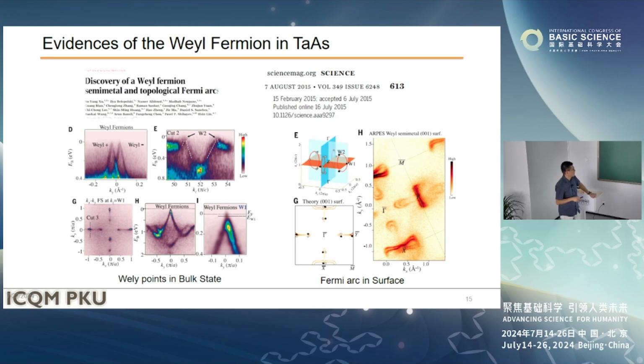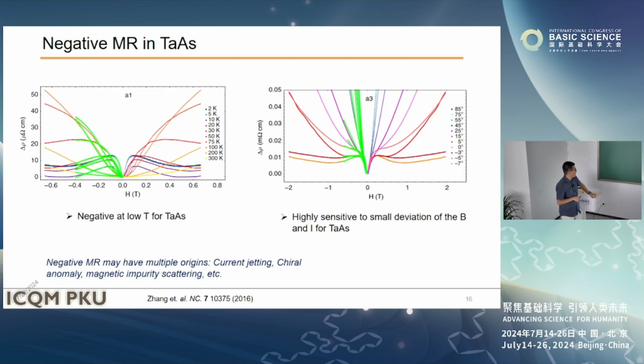ARPES experiments on this compound, and it was published in 2015. And they found the Weyl points in bulk states, the band crossing point, and also, more importantly, the Fermi arc at the surface. Both give solid evidence for the existence of a Weyl semimetal in tantalum arsenide. Another point is whether we can find this chiral anomaly in tantalum arsenide.